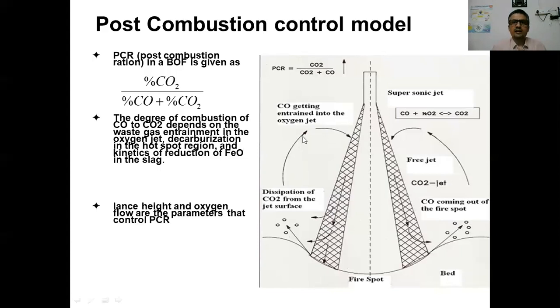This carbon monoxide gas, if it gets entrained into the jet, will again form carbon dioxide, and that is going to give you the post-combustion ratio. So the degree of combustion to CO2 depends on the waste gas entrainment in the oxygen jet in the hot spot region, and also on the kinetics of reduction of FeO in the slag. Both participate together. So in the overall sense, the presence of enough volume of slag is going to guide the post-combustion ratio. What I want to say is that the post-combustion ratio can in some way be used to predict the presence of slag above the liquid metal and its nature, whether the slag is dry or liquid.